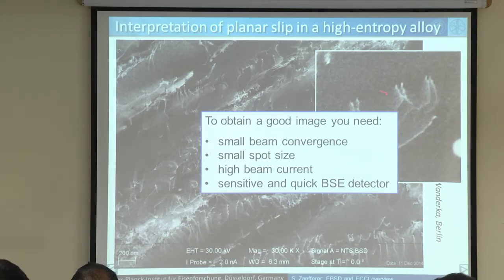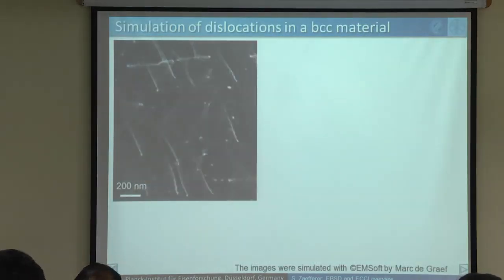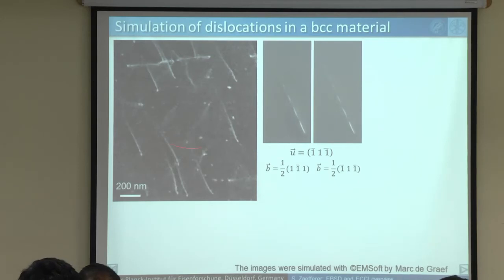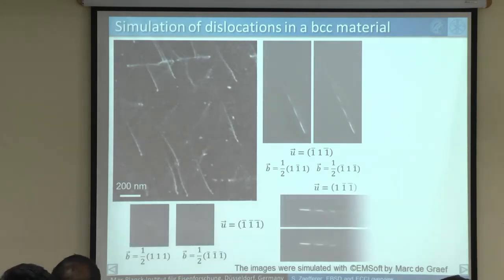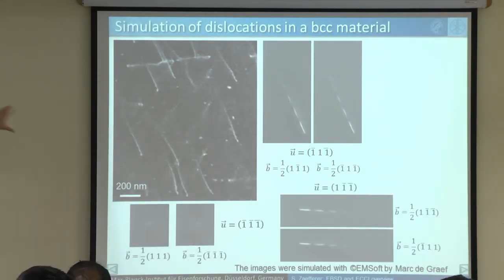But let me show you now, coming back to this picture, how we can understand whether these dislocations are dipoles or two following monopoles. For that, we have recently done calculations of this dislocation intensity, and we do this in collaboration with Marc De Graef at Carnegie Mellon University in Pittsburgh. He has special software, EMsoft, which allows that. And we calculate the appearance of these dislocations.